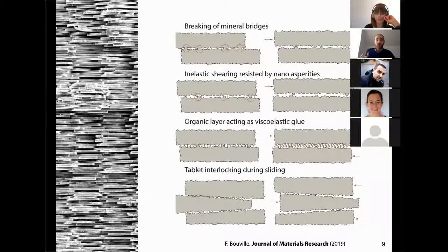And so if we try to summarize from this very simple assembly, what are the different reinforcing mechanisms that could happen during the failure of this material? Well, the first thing that we'll have to do to make these platelets move, to dissipate some energy during fracture, is break these tiny mineral bridges. And once these are broken, because the platelets are not perfectly smooth and they're very tightly fit together, these asperities are going to induce some friction when you try to move them.